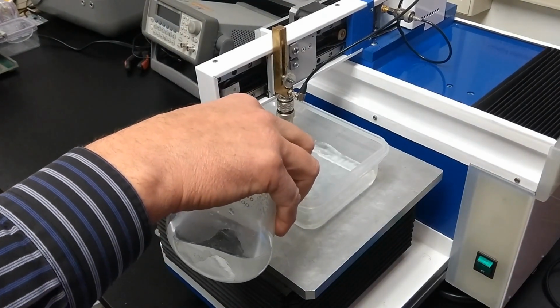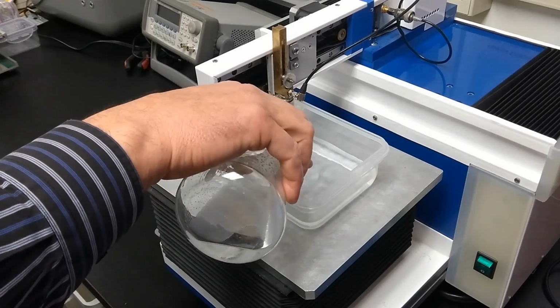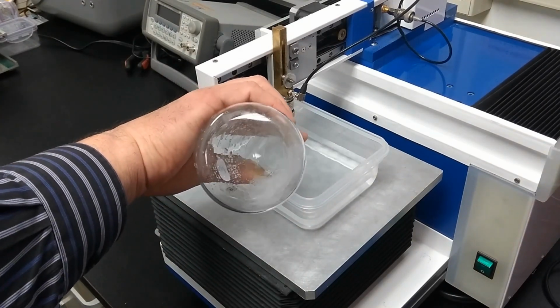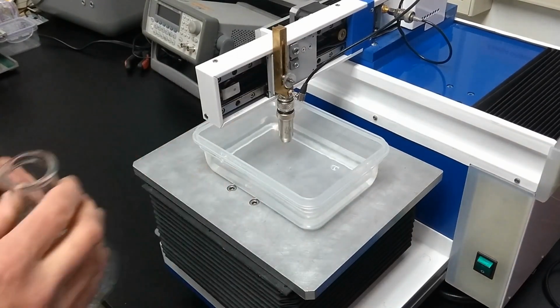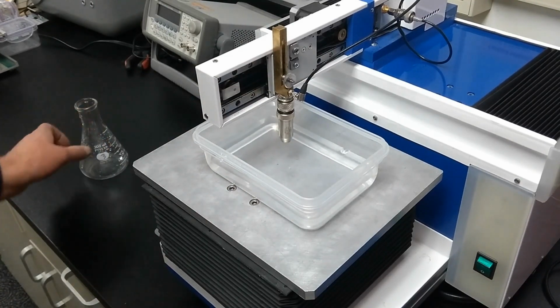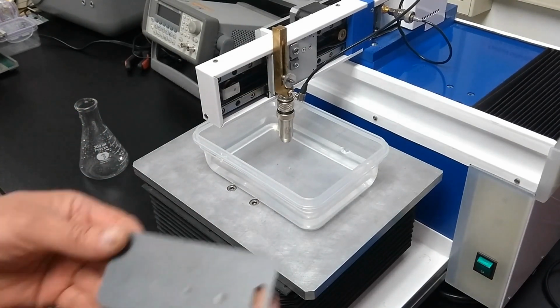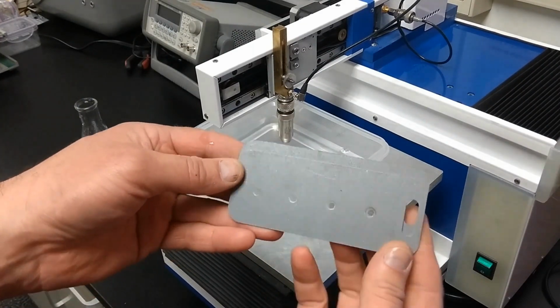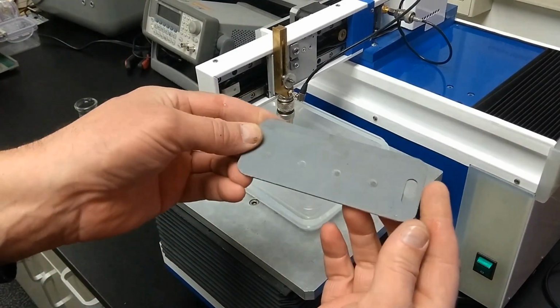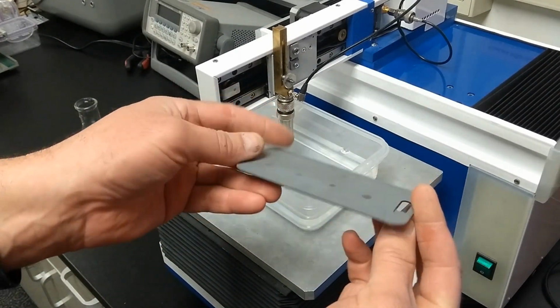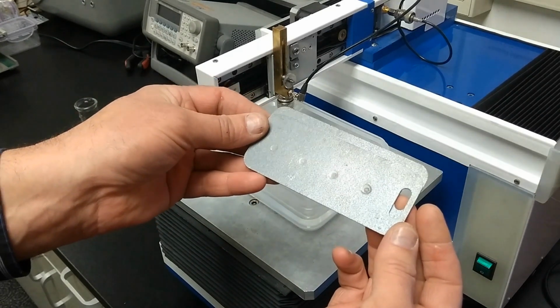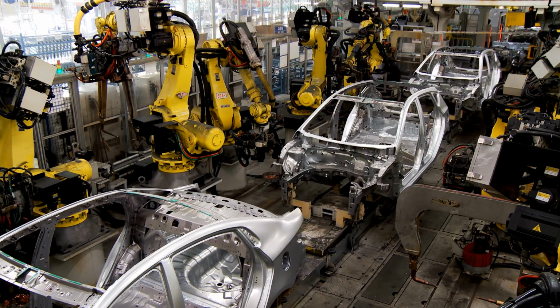The water has been allowed to sit undisturbed in the bottle for a day in order to settle and remove dissolved air. For this demonstration, we will be looking at a spot weld coupon. This is two metal plates, roughly 2 mm in thickness each, held together with a variety of spot welds ranging from 2 mm to 8 mm in diameter.